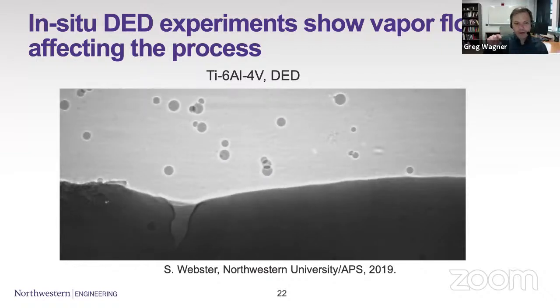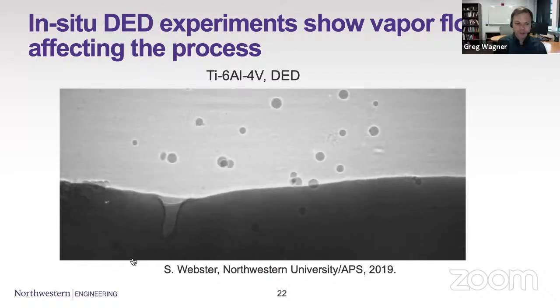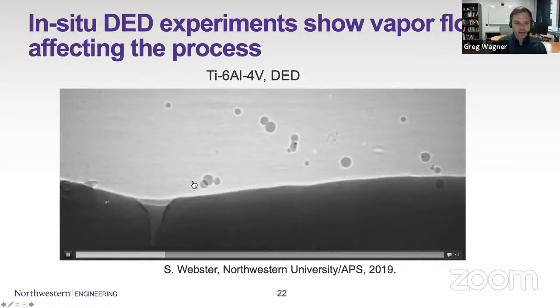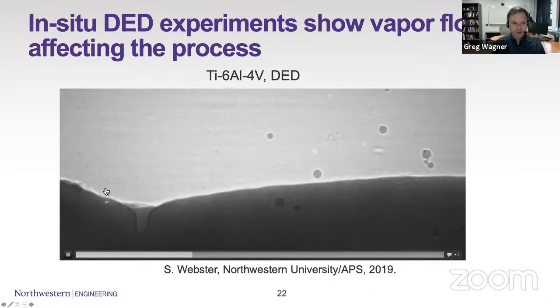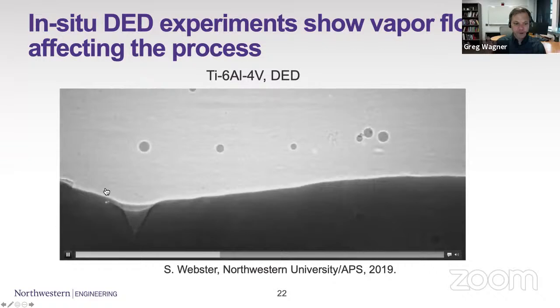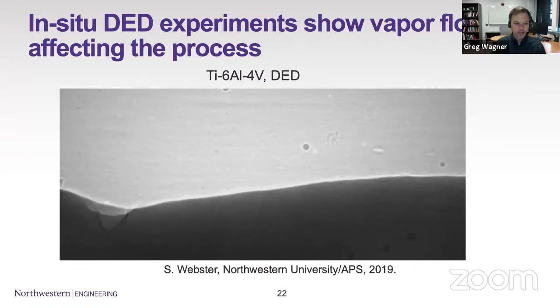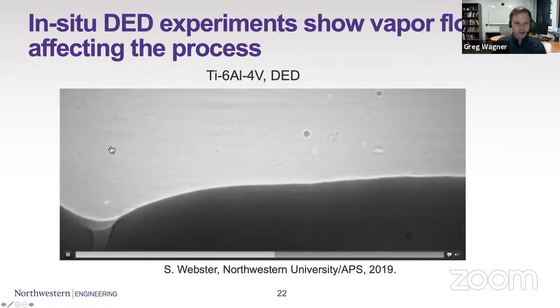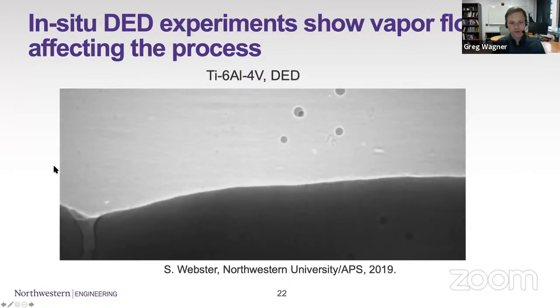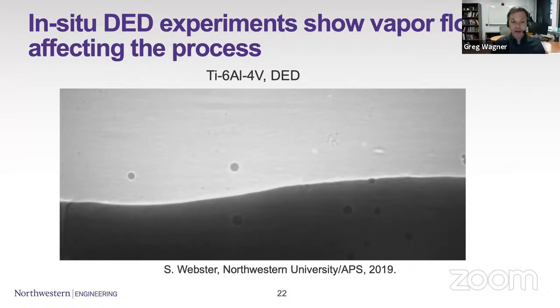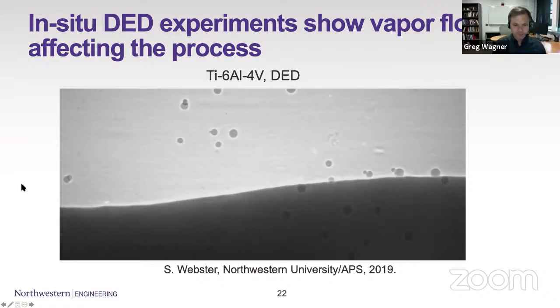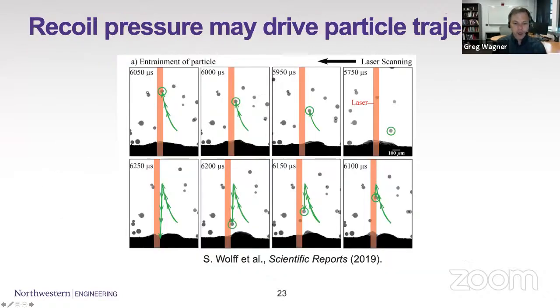This is of a DED process. In this case, the powder is being injected and not blown at a high rate, but you can see a couple of things here: there are interactions between the powder and what is clearly some kind of vaporization plume coming from the melt pool. These powder particles are getting entrained in the vapor. And so there's this clear interaction between the melt pool, the surrounding vapor, and the powder that's being injected. These are all things that we'd like to be able to understand. One interesting phenomenon, again, these are our collaborators in the experimental group here at Northwestern.